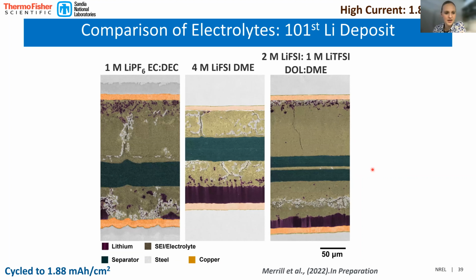At high current, the behavior was not as good as low current. There was still some residual lithium in the carbonate electrolyte, but it looks like it's fairly disconnected from the rest of the cell, because we see these cracks and these pits that have formed around the lithium inventory at the bottom, and so we don't really think that that's probably active lithium, that it's been restricted from access, and the electrolyte's been mostly consumed, so there's no longer transport in that cell.